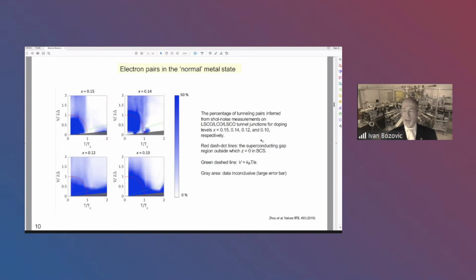This is work in collaboration with Doug Natelson at Rice University by shot noise measurements, which directly measures the charge of the carriers that tunnel in tunnel junctions, which were lanthanum-strontium cuprate based. So what we found is that a large fraction of electrons remains paired deep into the so-called normal state. That means at temperatures well above Tc and at energies way above the superconducting gap. And this, of course, is a very tough challenge for any Fermi liquid or BCS type theory.